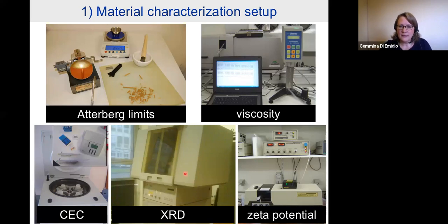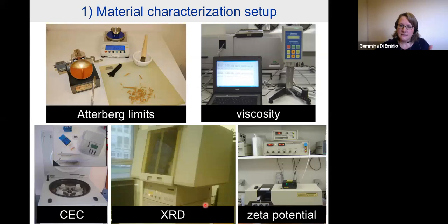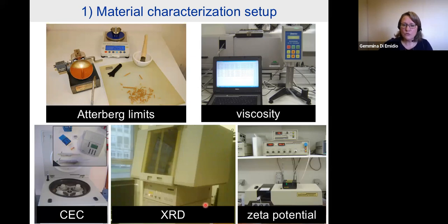Another method to characterize clay is XRD. This equipment is used to represent the clay mineralogy and distinguish different clay types — for example, whether a clay is kaolinite, illite, or montmorillonite. The clay normally used for barriers is bentonite, containing a large amount of montmorillonite, and XRD can quantify this content. For polymerized clays, this method is also very useful as we will see. Zeta potential is another method used in my PhD to measure the negative surface of the clay as a function of pH.